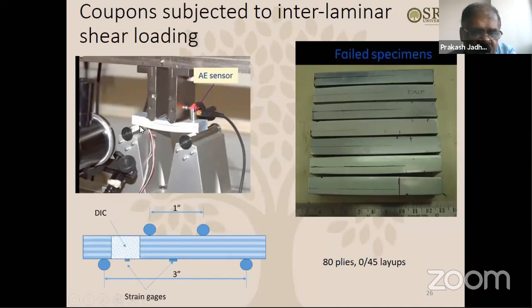When the testing is going on, of course, if the testing goes on for 20 minutes, for the first 10 minutes you will not see anything. No sound events we'll see. But when the crack initiates, suddenly the number of sound events start jumping up, and then after that they increase exponentially. Okay, so this is the simple setup. You can see 4-point bend short beam shear, and this is the region where we wanted to focus, because of course in this kind of boundary condition, this region will be having the highest interlaminar shear.